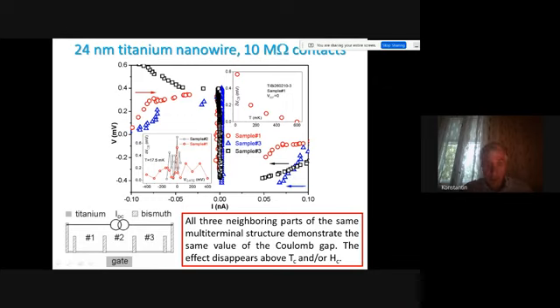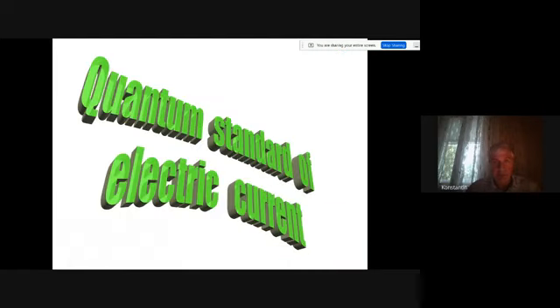And all of them indeed showed the Coulomb blockade. So at sufficiently small voltages, the current is not going. It is the insulating state of a superconductor. The amplitude of this Coulomb blockade oscillates as a function of the gate voltage applied to a nearby electrode and disappears above the critical temperature of the system. So it is indeed something related to the superconducting state. It's not just a conventional Coulomb blockade.